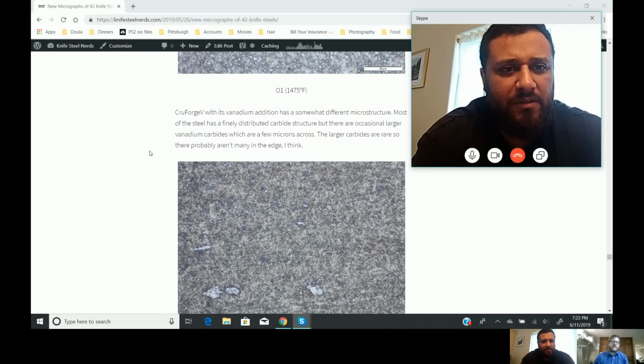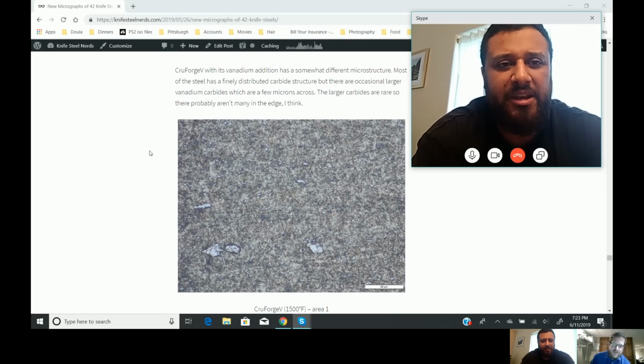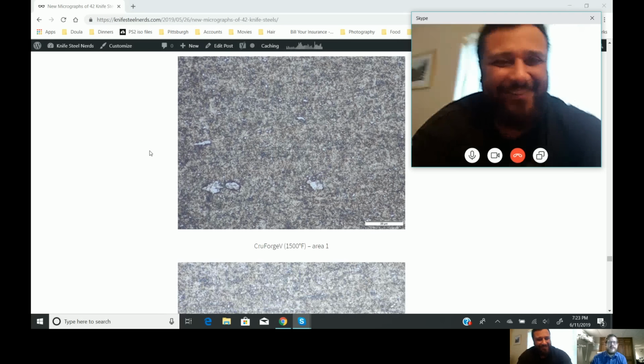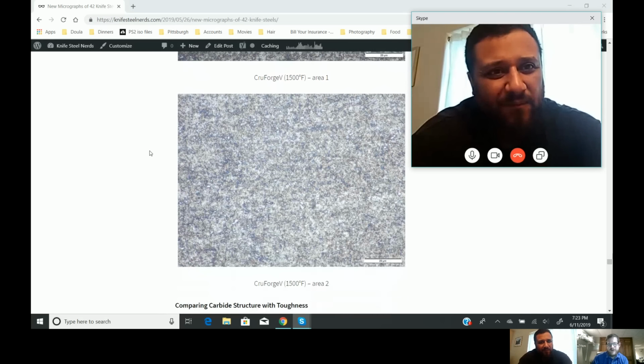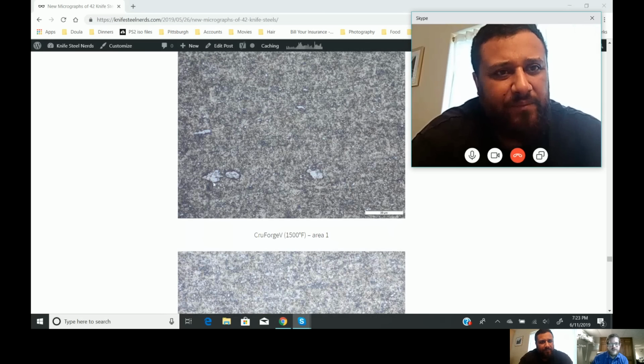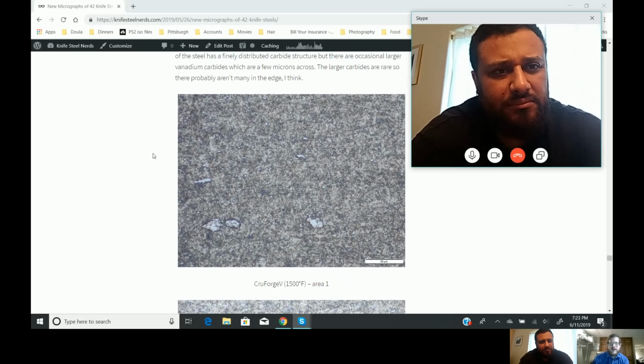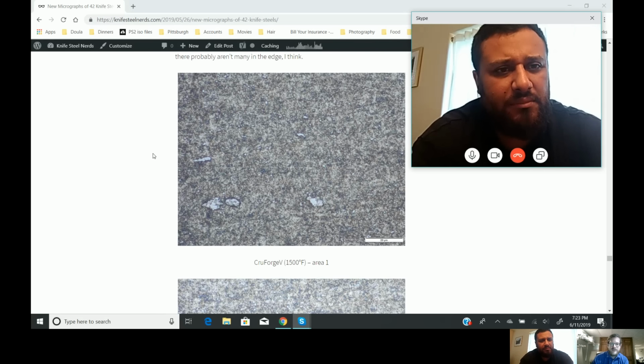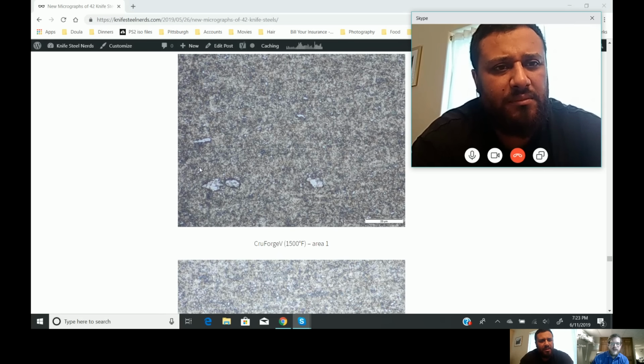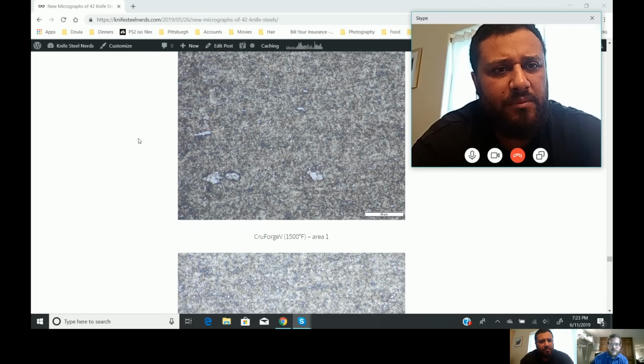Cruforge V is another forging steel with a little bit of wear resistance to it. Yeah, and so this is another one. You can see that there are some areas that have a little bit bigger vanadium carbides in them. Not enough to drop its toughness that much in the testing that we did, and there's so few of them, it probably doesn't affect your edge that much either.